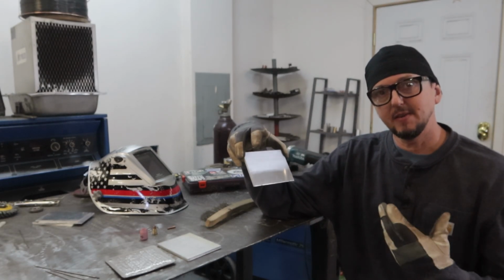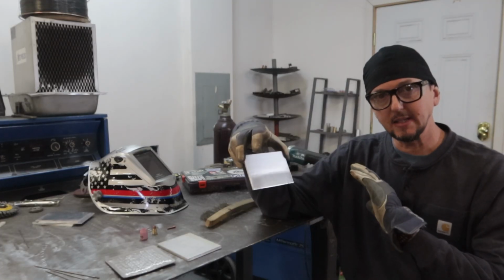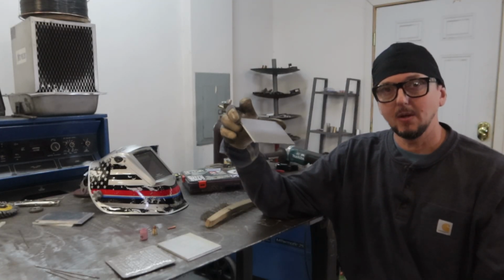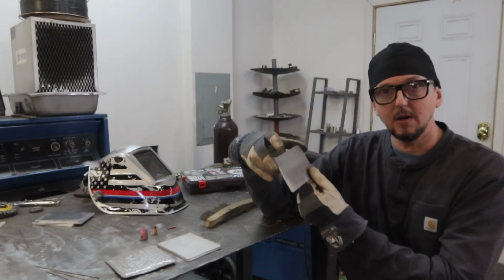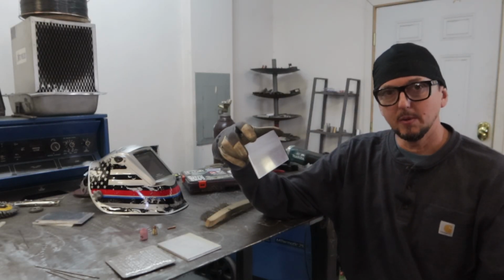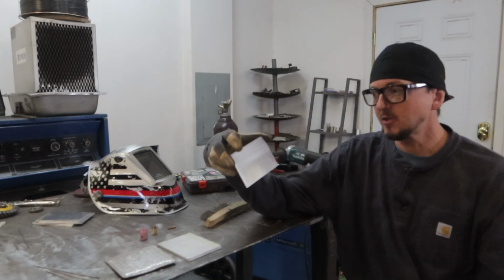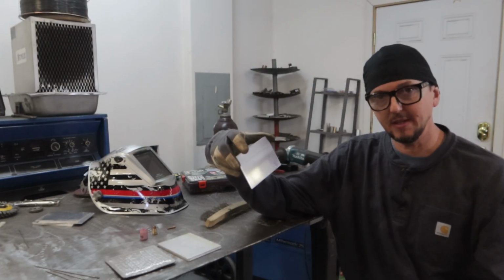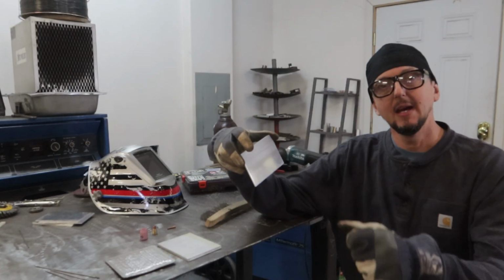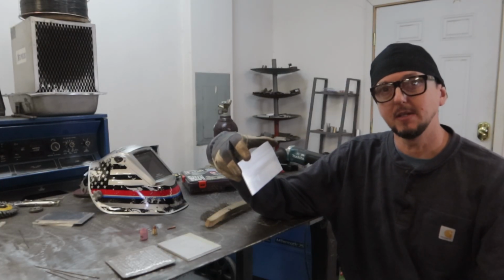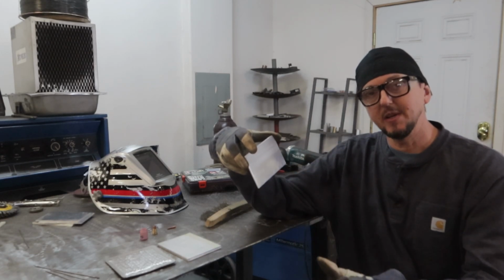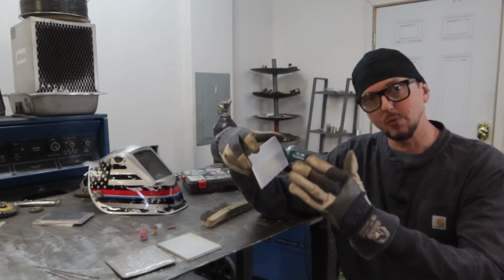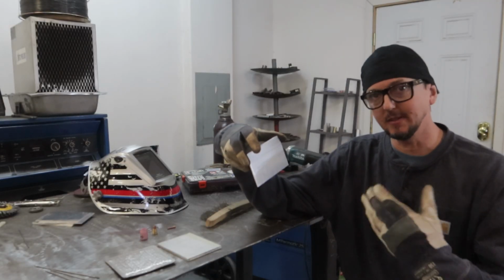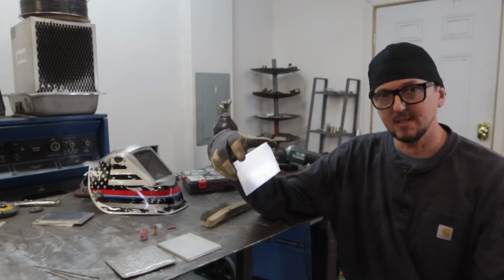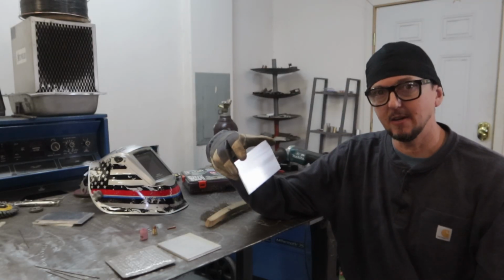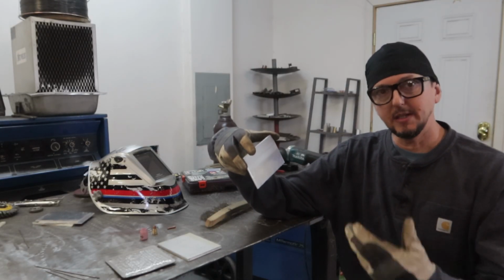And then also, because it's very prone to contamination, we would also want to clean the surface with a cleaner like isopropyl alcohol or acetone to remove any contaminants. And typically what we do in industry is we clean the material first with either alcohol or acetone, and then we brush our areas that we're going to be welding, and then we clean it again with those solvents to be able to remove any excess oxide or further contamination that was still left there. And that's going to give us our best case scenario in terms of cleanliness and weld quality and appearance.